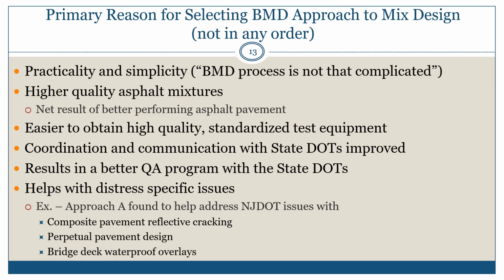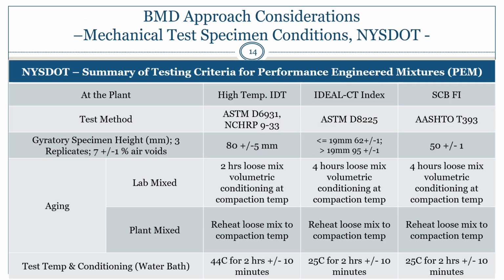As I mentioned earlier about the balanced mix design criteria for an agency, you can see here is New York State Department of Transportation as a quick example. You can see that they have both a rutting test and the high temperature IDT, and they're currently looking at two cracking tests, the IDEAL-CT and the SCB flexibility index, as test methods that they've included in their balanced mix design approach. They've done a very good job at describing the test method, describing the specimen size, the heights